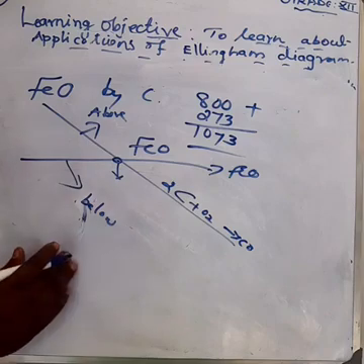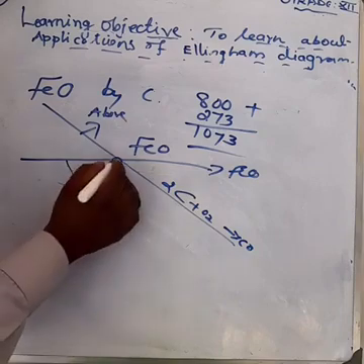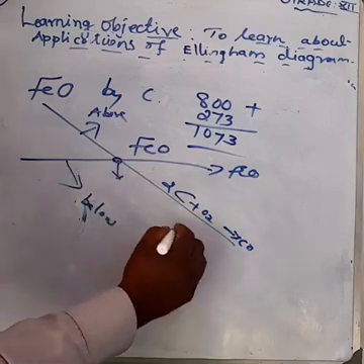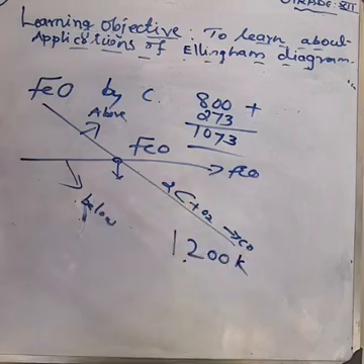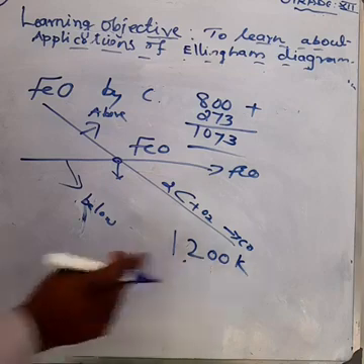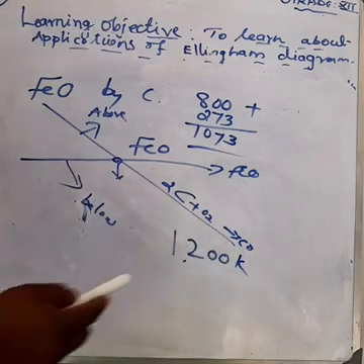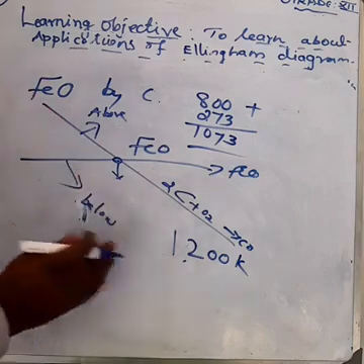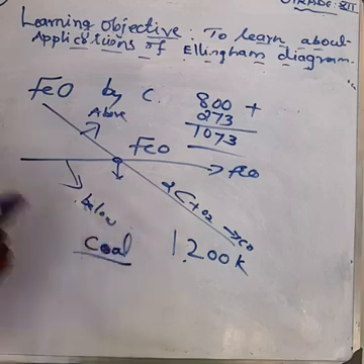And one more point, when we compare with carbon: above 1000 Kelvin, maybe 1200 like that, the carbon line lies below the iron line, and we use coke, that is carbon, as the reducing agent above this temperature.